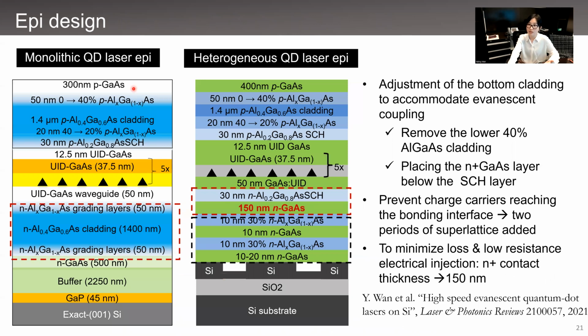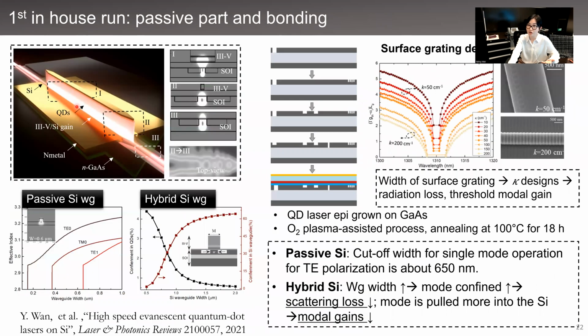So for the epi design, we started with the material stack for monolithic quantum dot lasers, and the transition to a design for heterogeneous integration requires adjustment of the bottom cladding to accommodate evanescent coupling, which is obtained by removing the lower 40% AlGaAs cladding and placing the N-GaAs contact layer directly below the 20% AlGaAs separate confinement heterostructure layer. To prevent charge carriers from reaching the bonding surface and causing non-radiative recombination, we adopt periods of superlattice to minimize the loss, and to allow for low-resistance electrical injection, the N-contact layer was optimized to be 150 nanometers. So here is the schematic showing the quantum dot laser integrated on SOI, consisting of a hybrid III-V silicon active region coupled to passive silicon waveguides on two ends.